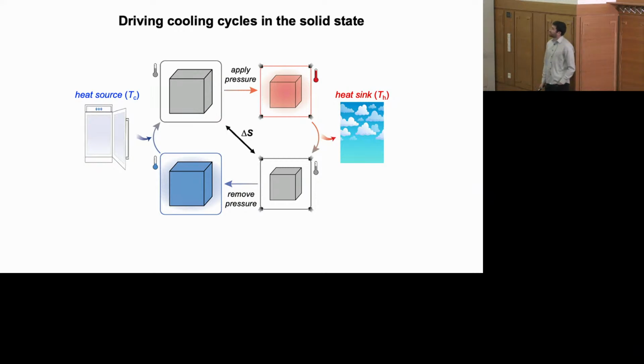If you think about doing this, you need the ability to have a solid material that can go between two states that have the same temperature, but in which you've been able to dissipate excess heat to the environment and then take in more heat. And so the only way you can think about doing this is if you have two states of a material that can exist isothermally at the same temperature with very large differences in entropy. And the differences in entropy between these two states of the material is going to be directly related to how much heat you can withdraw on a particular cooling cycle.